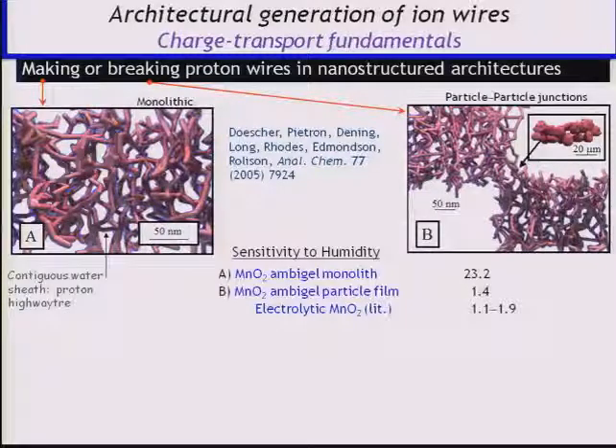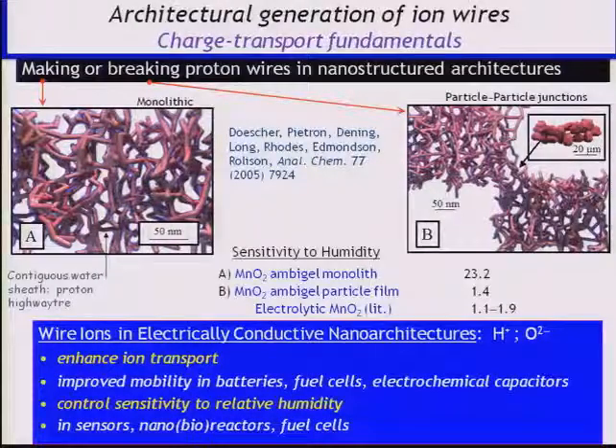So if you want to do any kind of conductometric sensor, you would like not to break the wires between points in the film. So you should be able to enhance ion transport. This should help us improve the mobility of ions in electrochemical power that we care about. Of course, we can change our sensitivity to humidity. And I've put the proton here. Well, this makes perfect sense. It's easy to imagine a sheath of water adsorbing at these oxide scaffolds.